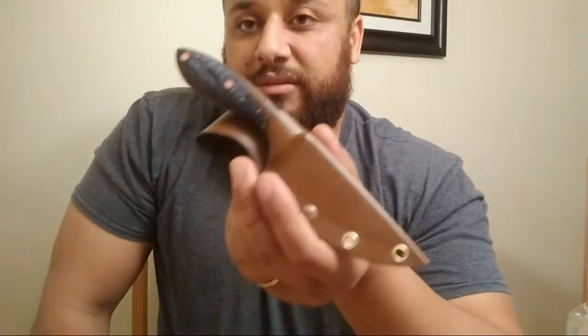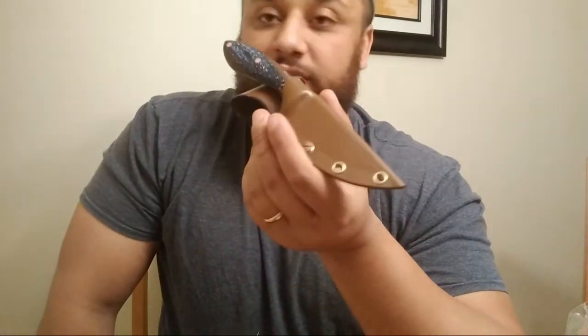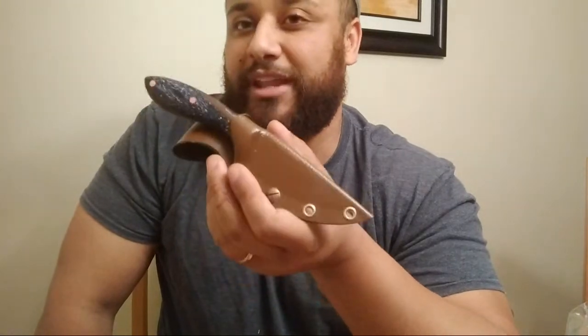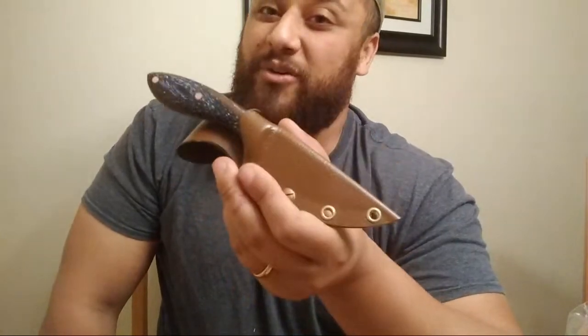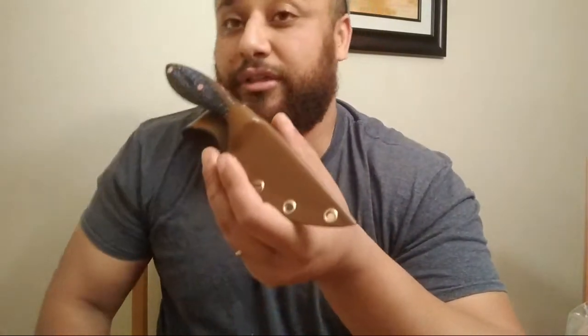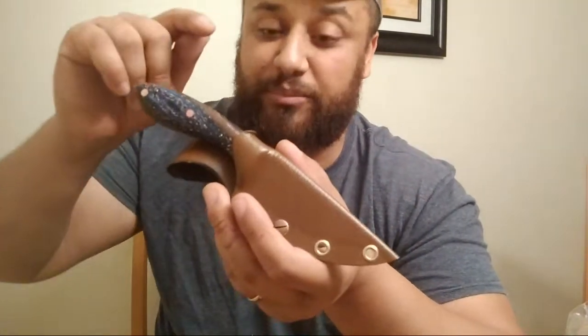So with Vancron, because we replace vanadium carbide with vanadium nitride, and the process they use to get nitrogen in the steel, it will make these vanadium nitrides very, very fine. And so these vanadium nitrides are about 1 micron. And so the idea, the theory is that the finer the carbides or particles inside the steel, in this case, these particles are nitrides,